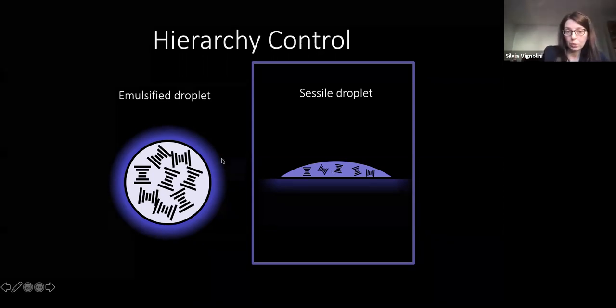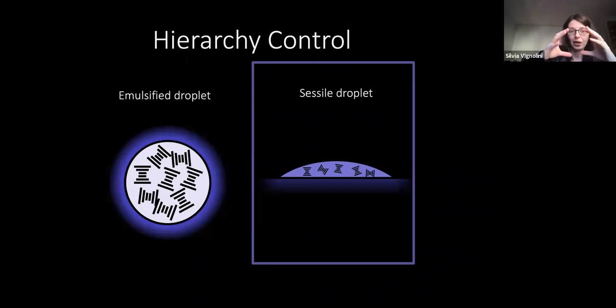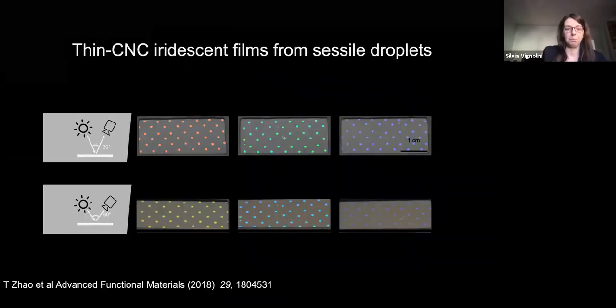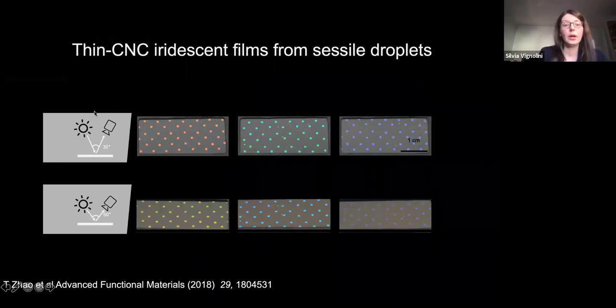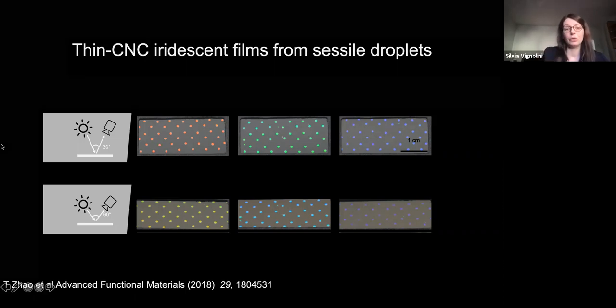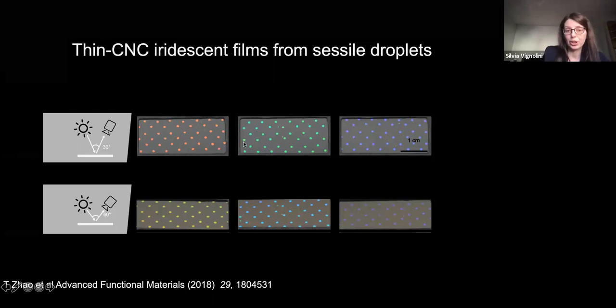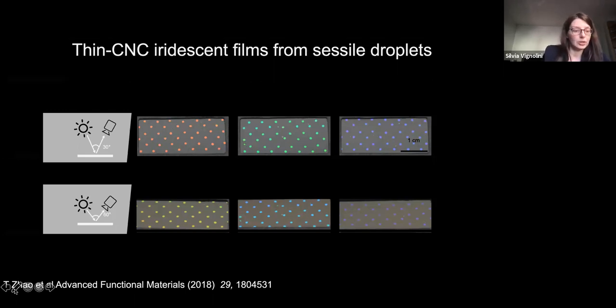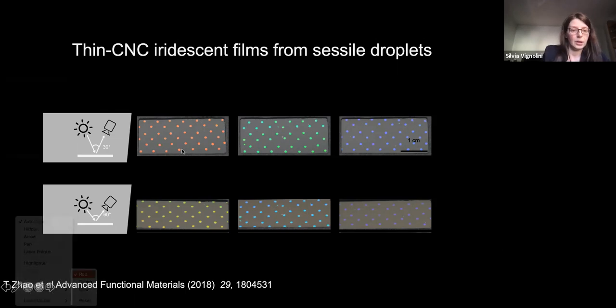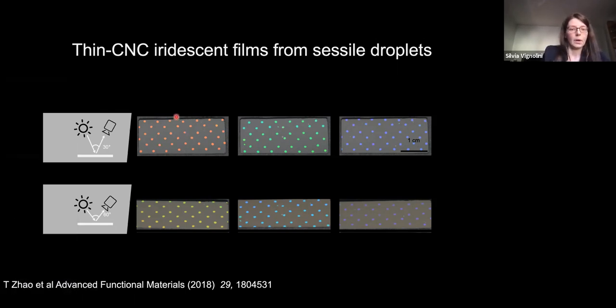The first would be more similar to the case of a pigment, more similar also to what you have in plants, because you remember the cell architecture is kind of spherical. And this other is something more similar to when you, for example, print and create a film. In fact, we actually have used a printer. This is a printing method. And in the same way that we can make films of different color, you can simply change the amount of salt in the suspension. And what you can do is change the coloration that you print, let me just take again this laser pointer. You can essentially go from red to green to blue.